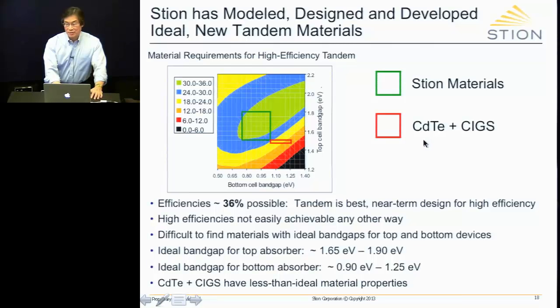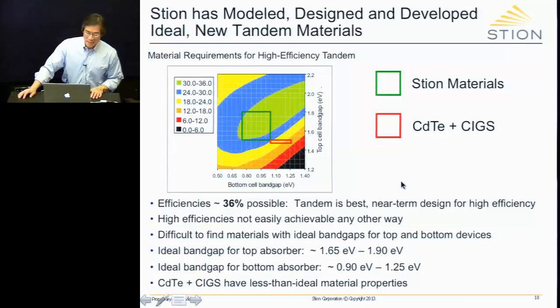And that's because cadmium telluride is 1.5 eV. Now, some of the researchers here at Stanford are working with putting in zinc and others to change the band gap of cadmium telluride, for example. And that's a great direction to go. The biggest problem with the 2-6 system is cadmium. You will find that oftentimes in life, logic doesn't win out. And in this case, even though it is a great material system, I love Telluride incidentally, the fact that cadmium is there is a big problem.